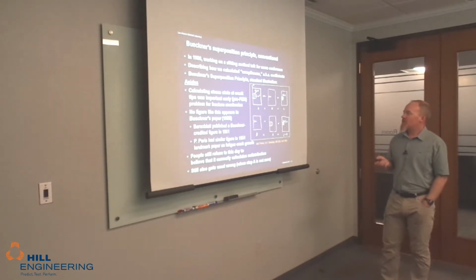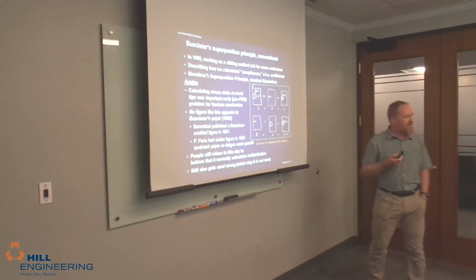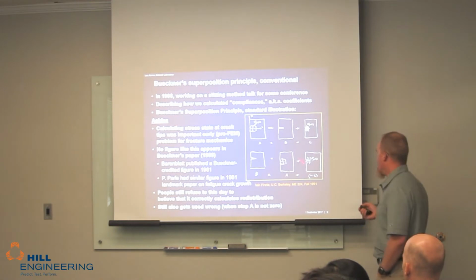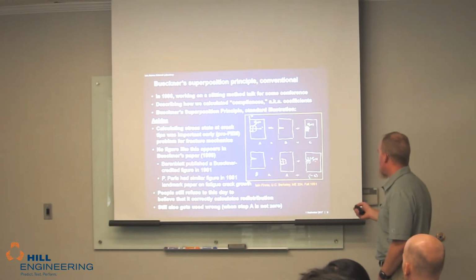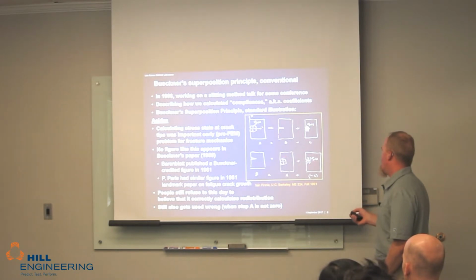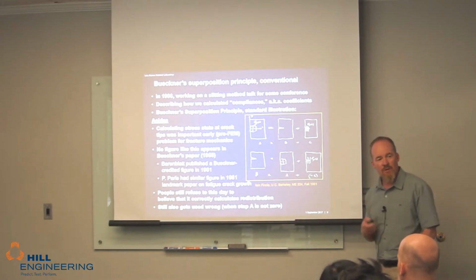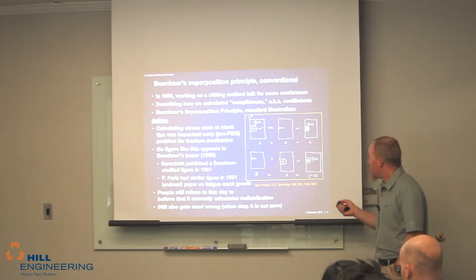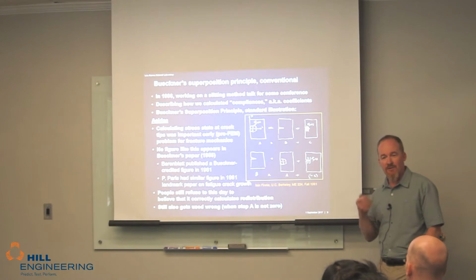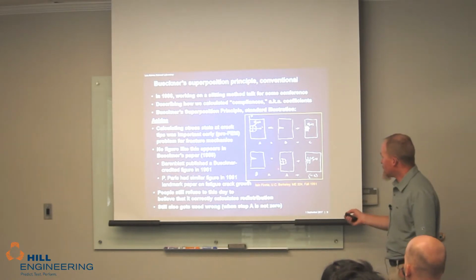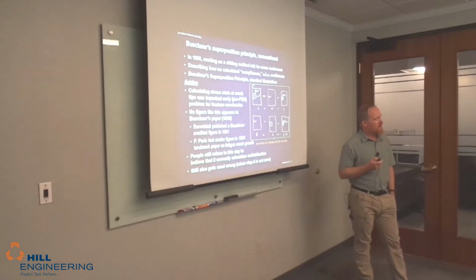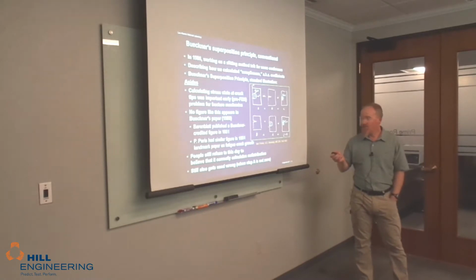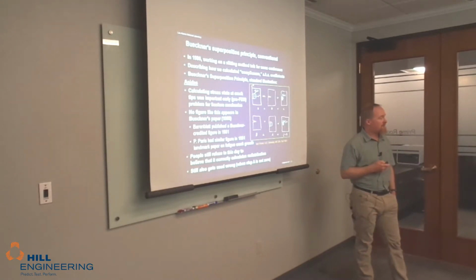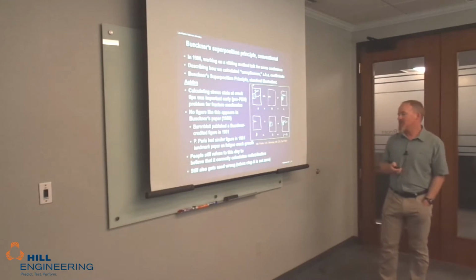I've seen people use this for hole drilling and for slitting to calculate yielding effects, to look at plasticity, where they'll do this kind of calculation to calculate yielding at the crack tip. And for something like yielding, you can't ignore the stresses here. The deformations here are 0, so you can ignore it for that. The K1, the stress intensity factor, is 0 because there's no crack there. But the von Mises stress in this stress state is not 0. So if you use this to calculate a yielding effect, you're missing part of the stresses. People do that as well. So you've got to understand what this principle can do and what it can't.